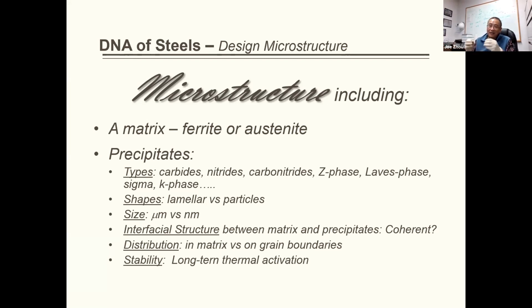If you have one precipitate that gives you good properties at room temperature, when you put it in a boiler running at 1,000 or 1,050 degrees, at elevated temperature the microstructure is going to begin to degrade. The main degradation is in the precipitates. The precipitate is going to grow, and the size and interface structure are also going to change. A lot of people have studied this.